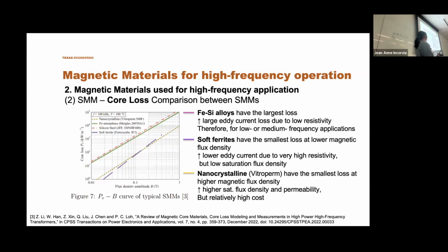By comparing the other magnetic properties we've seen before, we can assume that the iron silicon alloys have the largest loss because they have a very low resistivity, which gives them a large eddy current loss. Also, soft ferrites have the highest resistivity, which gives them a small loss, but because they have low saturation flux density, they have only been used at the lower magnetic flux density. Lastly, since the nanocrystalline alloys have the overall best parameters for operating at high frequency, they had the smallest loss at the highest magnetic flux density.